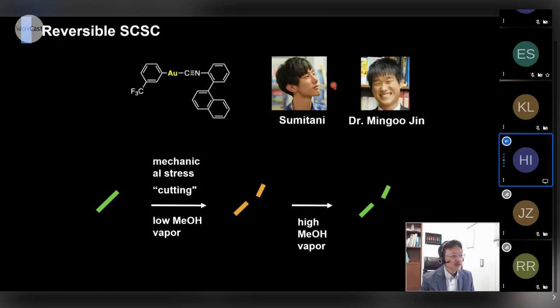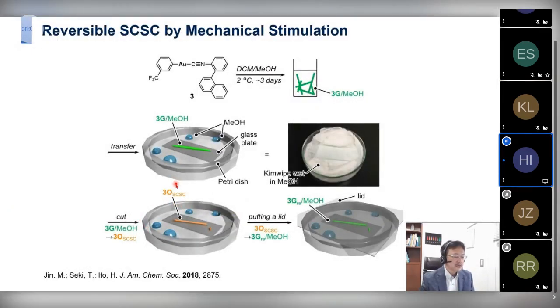So we then tried to synthesize a reversible single crystal to single crystal transformation induced by mechanical stress. In the first movie, I showed the reversible mechanochromic luminescence property, and in the second part I showed the single crystal to single crystal phase change. But in the second case, that cannot be reversible because after the phase change, this structure is thermodynamically more stable compared to the pristine structure. But we tried a single crystal to single crystal version of the reversible mechanochromic luminescence by just changing the methanol vapor. So this is the experimental setup of this study.